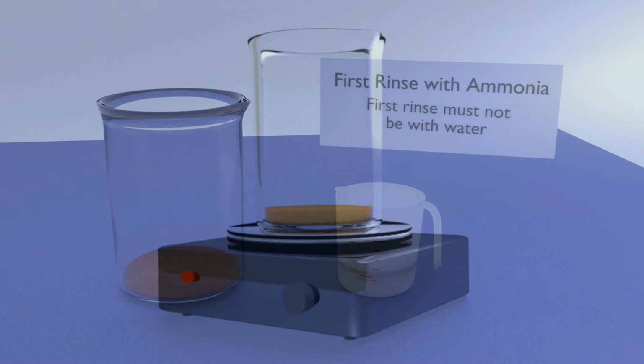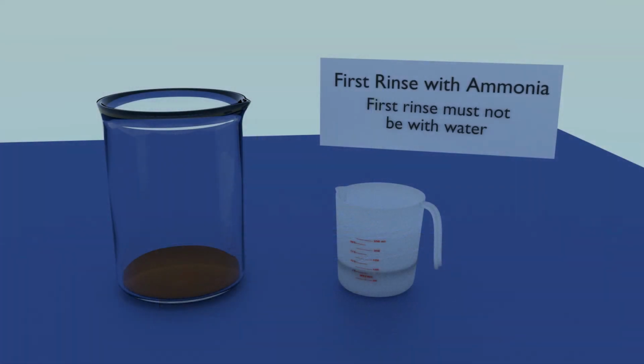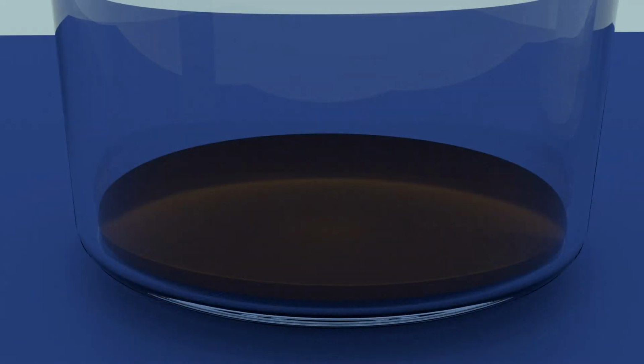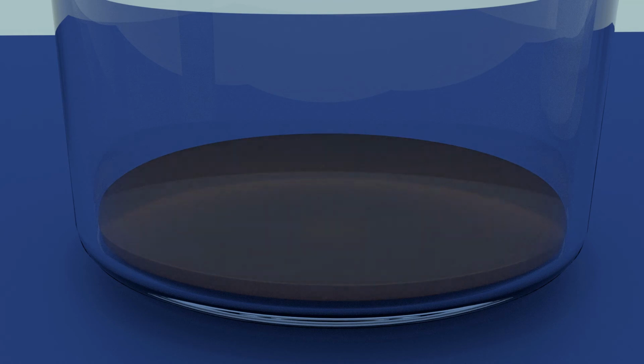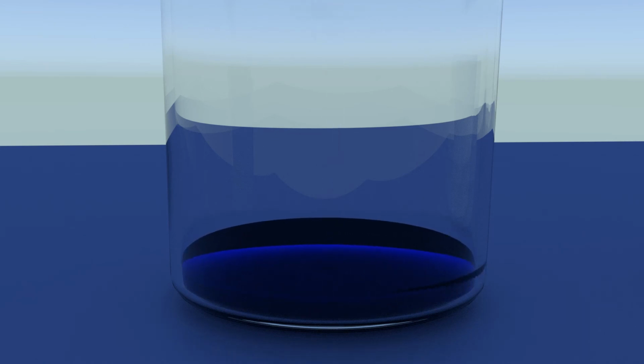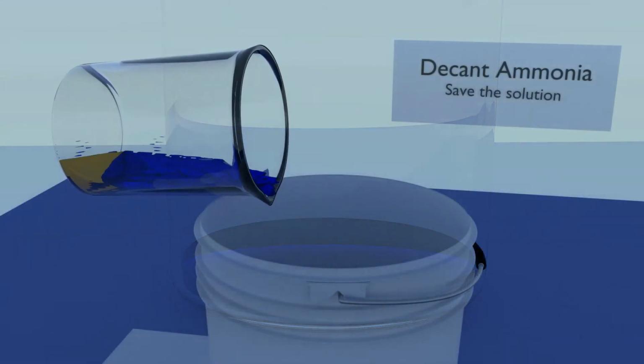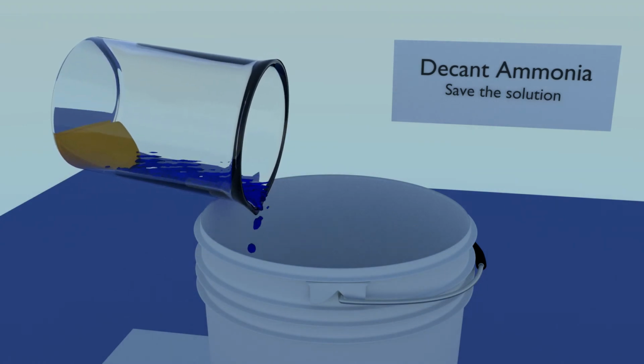For the first rinse only, ammonia, not water, must be used. The reason is this. If the first rinse is with water, copper hydroxide can precipitate, coating and contaminating the gold with a white, sticky substance. Add at least enough ammonia to cover your gold mud. The ammonia will rapidly turn blue, as it reacts with a small amount of acid that is still clinging to your gold mud. Decant the ammonia, saving the solution.